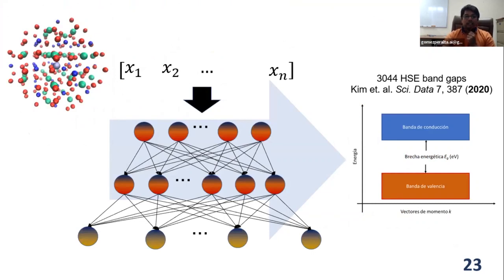Another question that we had is if it's possible to use features extracted by the trained artificial neural network to estimate the band gap of a material. If so, the artificial neural network can be used to find compounds with a certain crystal structure alongside the band gap. And basically, we tailor these compounds by selecting some atoms and proposing a structure. And recently, we have used the features extracted by one of the trained artificial neural networks to create an input vector useful for a convolutional neural network to assess the band gap.